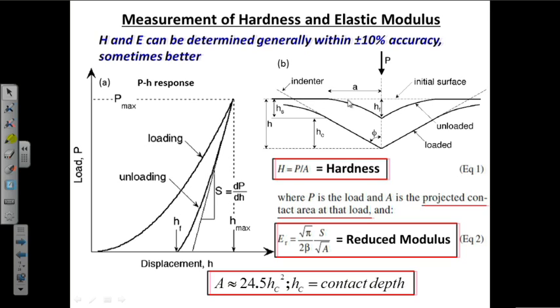In figure B, I have shown the profile of an indenter. The horizontal dotted line shows the initial surface of the material. If we apply a certain load P, the indenter penetrates a maximum depth which is given by H. It is interesting to see that the indenter, which is shown by the inclined dotted line, is not always in contact with the material. It is in contact with the material until a certain depth, which is called the contact depth and designated as HC. Now if we unload the indenter, the material recovers a certain depth, and the residual depth is given by HF, which is the final depth after unloading of the indenter.